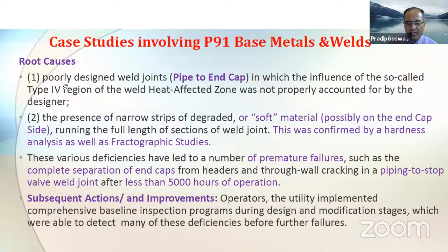What was established is that the poorly designed pipe to end cap weld joint influenced the so-called type 4 region of the weld heat affected zone. The type 4 region is basically a creep type. Creep is a high temperature deformation, a high temperature degradation of any alloy. Type 4 creep is a range in the creep deformation curve which is beyond repair. Once type 4 creep has set in any weld or heat affected zone, that's basically the death warrant of that component. It will progress and it will fail at any point of time.